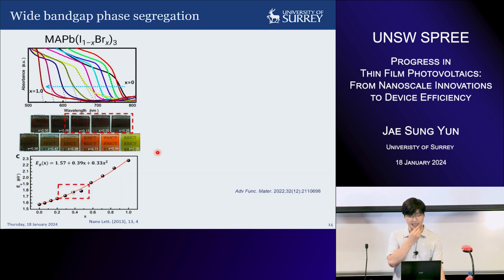So as I mentioned, you can tune the band gap of perovskites. To do this, we need to change the composition of the halides. So if you see, this is methyl ammonium lead perovskite, and if you have iodine only, which is this one, the band gap is around 1.6, so slightly less than 1.6, and you can gradually increase the band gap by putting more bromide into your material.